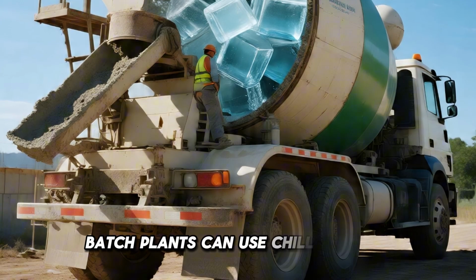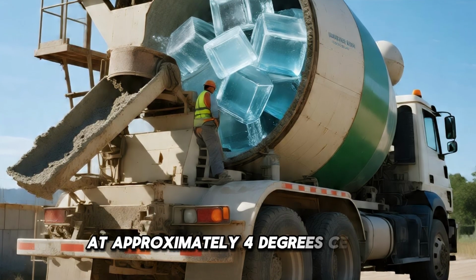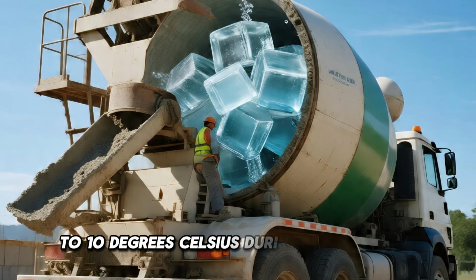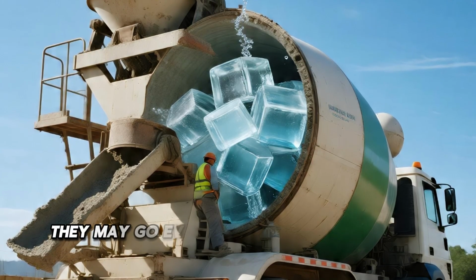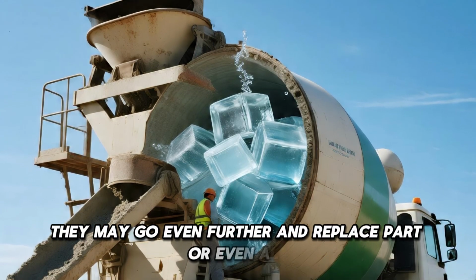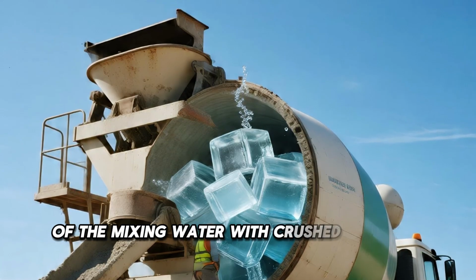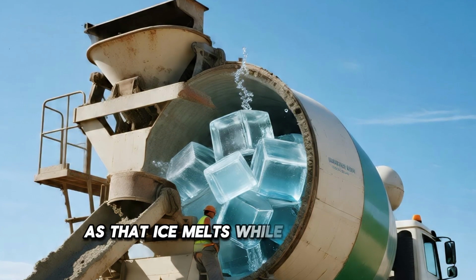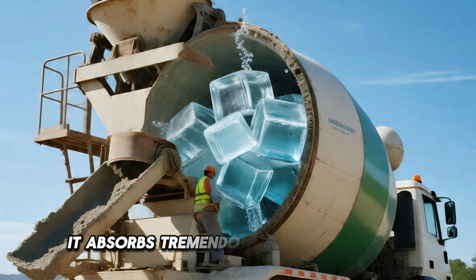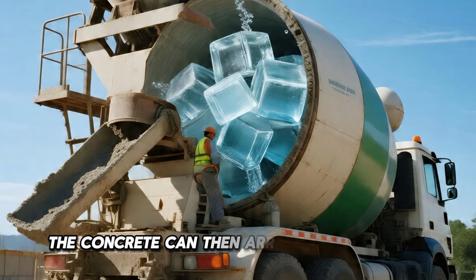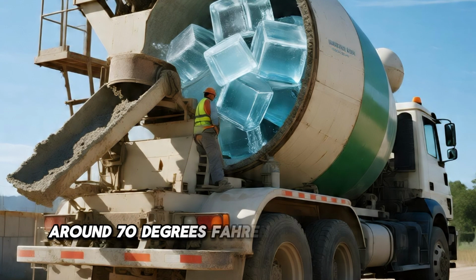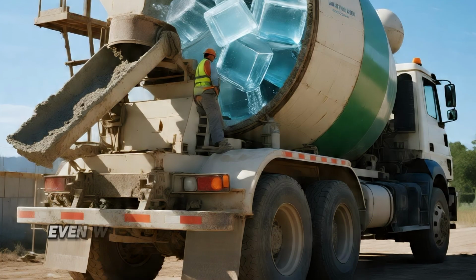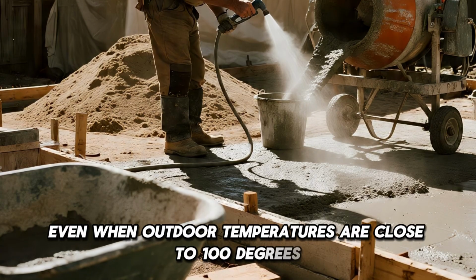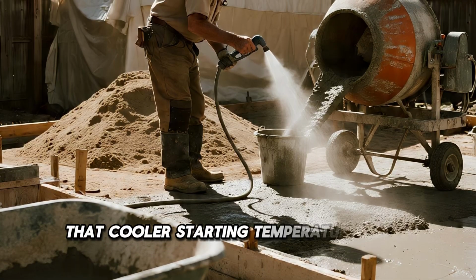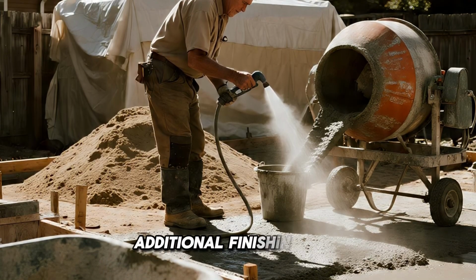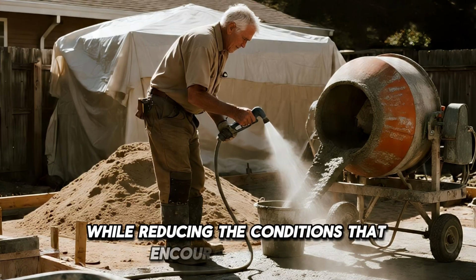Batch plants can use chilled water at approximately 4 degrees Celsius to 10 degrees Celsius. During extreme heat, they may go even further and replace part, or even all, of the mixing water with crushed or flake ice. As that ice melts while the truck is traveling, it absorbs tremendous amounts of heat. The concrete can then arrive at the job site around 70 degrees Fahrenheit to 80 degrees Fahrenheit, even when outdoor temperatures are close to 100 degrees Fahrenheit. That cooler starting temperature gives workers precious additional finishing time while reducing the conditions that encourage cracking.